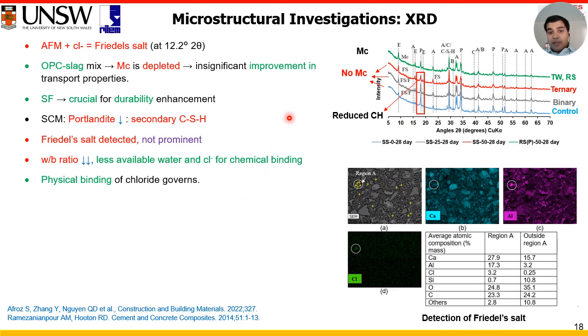From XRD analysis, we found that the Portlandite has significantly reduced in the ternary mixes compared to control, and we also saw that the monocarboaluminate in the OPC slag based mix was diminished. This is the reason why adding only slag will not provide a significant improvement in the transport properties, and this also emphasizes the importance of adding silica fume in this type of marine ultra high performance concrete.